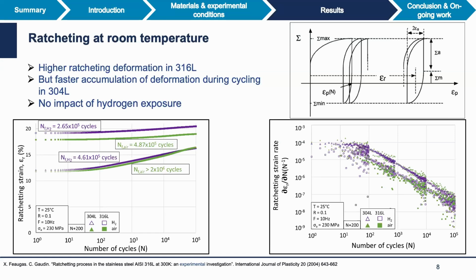And what we observe is that the progressive deformation is higher in the 316L, but the strain rate is higher in the 304L. And we cannot identify any influence of hydrogen exposure, which is not surprising because at this temperature, we cannot imagine that we have a significant ingress of hydrogen towards the bulk material. But what is important to note, however, is that in any case, you have, even at the very beginning of the test, a significant value of this deformation.